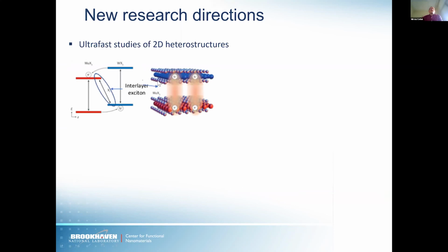So we are very interested in looking at ultrafast studies in 2D heterostructures. Heterostructures of different materials can be created. So in this particular case, the exciton, the electron hole, can be spatially delocalized, basically. So one electron can be on one material, and the hole can be on another material. We're interested actually in intercalating layers in between these active materials, so non-active layers, to see if we can slow down the recombination of the electron and hole, so make the excited state lifetime of the exciton longer, which is a property that counts for applications in photonics and quantum information science.